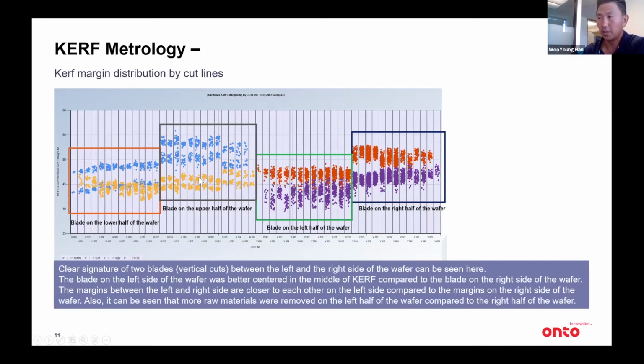So as you can see, for every cut direction, we can clearly see two signatures, right? And this is because a lot of the sawing machines are using a two-blade system to increase the throughput, right? So all these sawing machines have two blades that start sawing the wafers from each end of the wafer, right? So in this case, a lot of times we see a clear signature of two sawing blades.